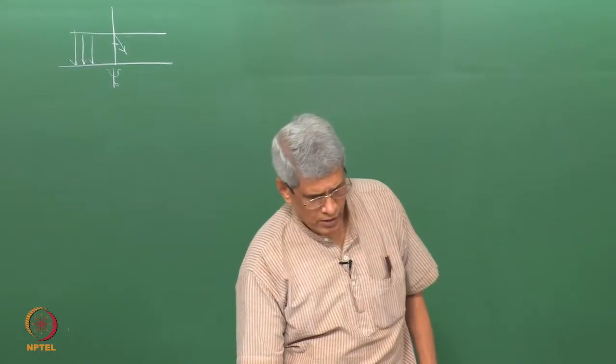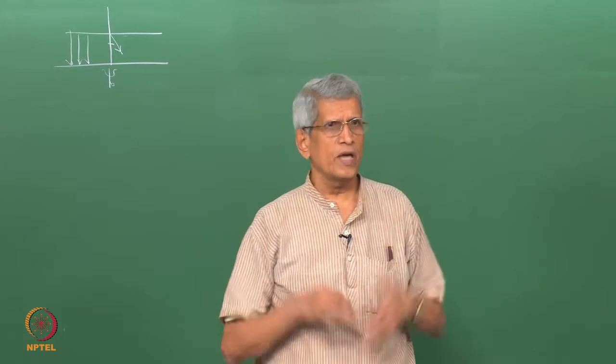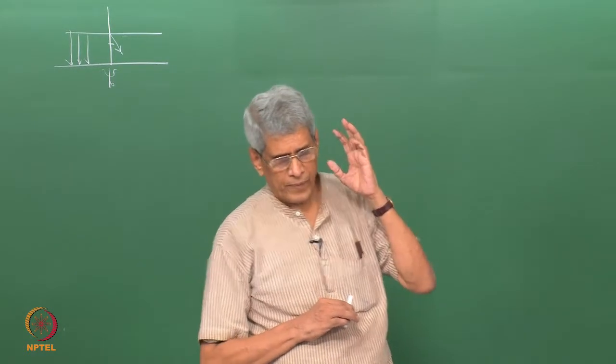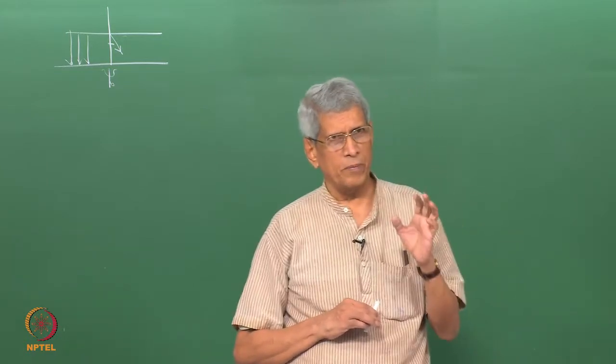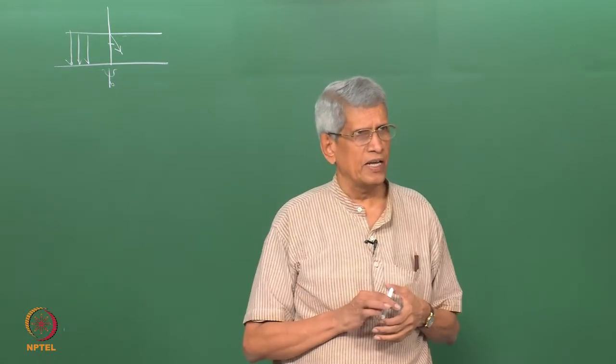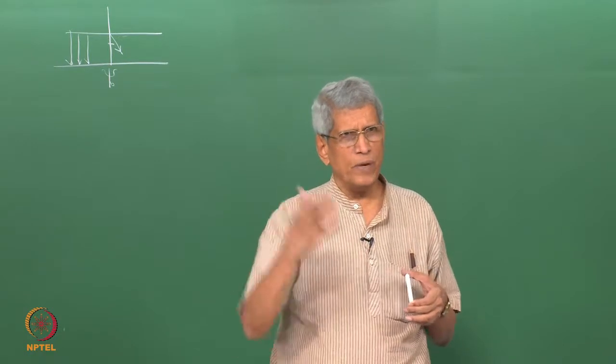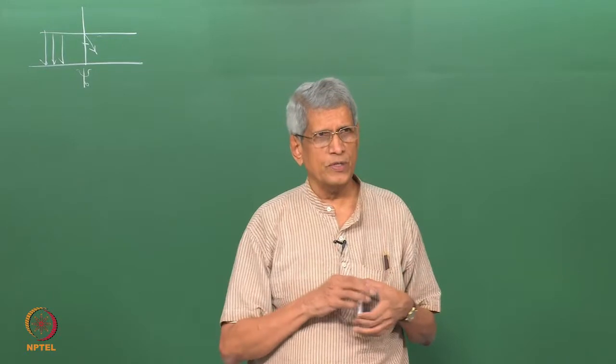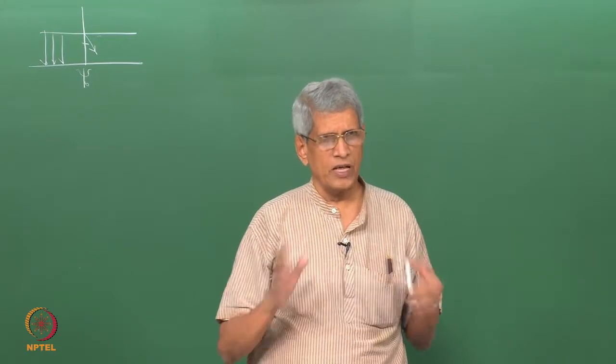When this coupled equation is solved, we are able to get the amplitude of the transmitted and diffracted beams at the back of the foil, and on that basis we could explain the fringe contrast which occurs in the case of a wedge sample.